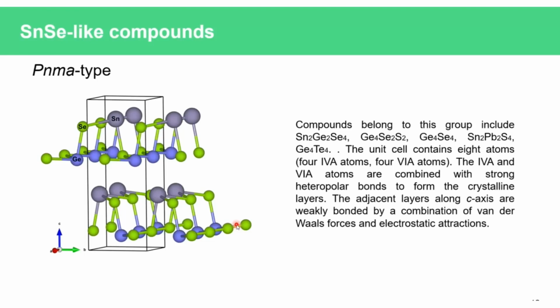Luckily, the structures extracted from the Materials Project include such compounds. Tin selenide has 2 phases: a low temperature alpha phase with space group PNMA, and a high temperature beta phase with space group CMCM. Compounds similar to the alpha phase include 5 ones. The unit cell contains 8 atoms and adopts a double layer structure. In each layer, atoms are connected in a distorted zigzag form. The adjacent layers along the z-axis are connected by a combination of van der Waals force and electrostatic attraction.